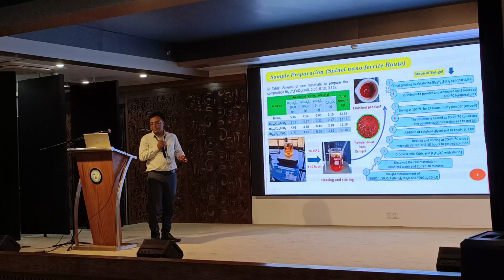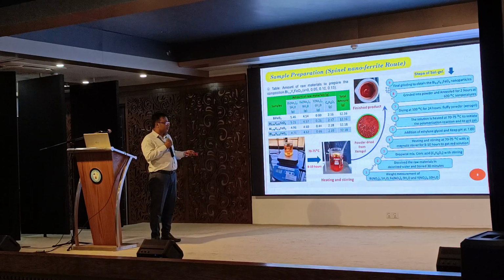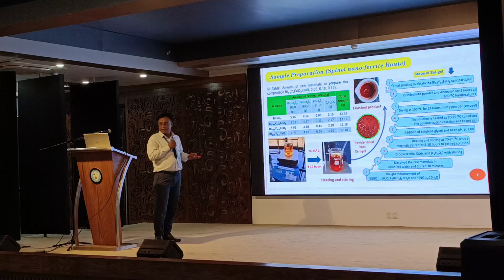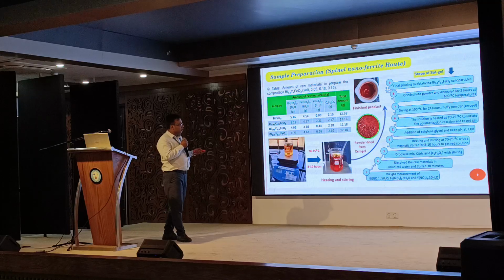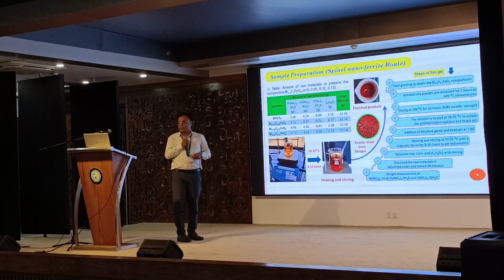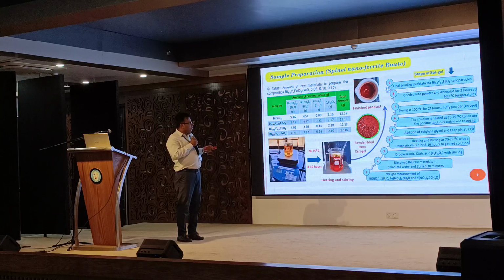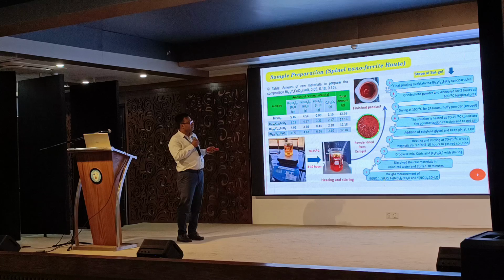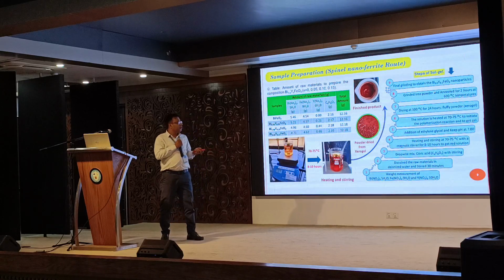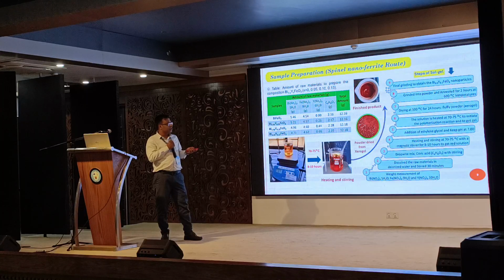We can start from nitrates as raw materials. Then we have to include some deionized water, and using the stirrer we perform 30 minutes of stirring. Then dropwise we mix citric acid into that solution. Then heating and stirring at 70 to 75 degrees Celsius with a magnetic stirrer for 8 to 10 hours to get the red solution. After that, we include ethylene glycol to keep the pH at 7. Thereafter, the solution is heated at 70 to 75 degrees Celsius to initiate the polymerization reaction to get the gel. This gel will be dried at 100 degrees Celsius for 24 hours.